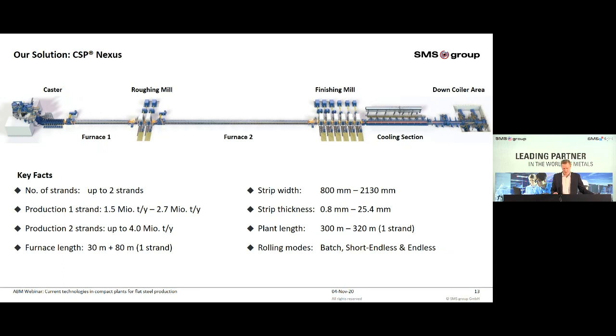The layout shows the basic Nexus setup with a casting machine, a tunnel furnace, a two-stand roughing mill, a second furnace, a 6-stand finishing mill, laminar cooling, and 2 downcoilers. The Nexus plant is capable to produce up to 2.7 million tons per year with 1 strand, and up to 4 million tons per year with 2 strands. As a 1-strand plant, furnace number 1 has a length of 30 meters, and furnace number 2 has a length of 80 meters. It is possible to produce strips with a thickness of 0.8 millimeters and up to 25.4 millimeters, and a width of up to 2,130 millimeters. The Nexus plant can produce in batch, short endless, and endless rolling mode.